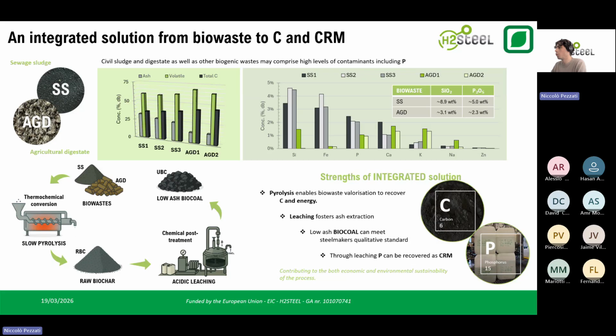To accomplish this, we propose an integrated technology solution in which first the biowaste streams are treated thermochemically by slow pyrolysis, which allows us to unleash the carbon potential of the material, removing the volatile matter and fixing the carbon in an inert form in the material.